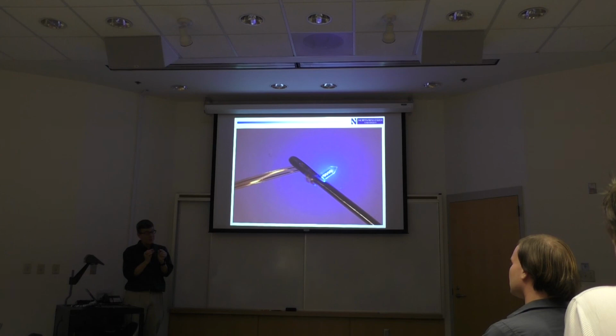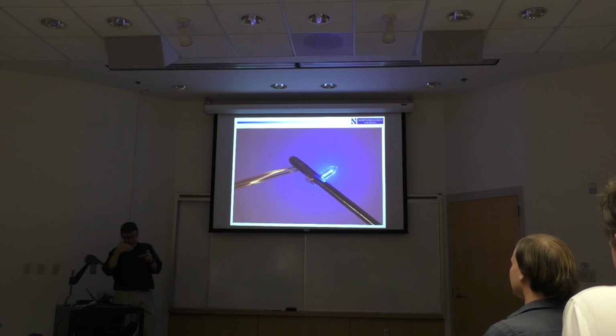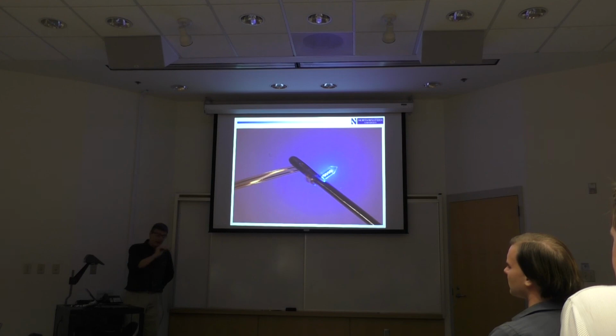And they do that because it's an effective way to keep the biofluids out. And unfortunately, we can't use that approach because 3 millimeters of titanium, and then we don't have a flexible device anymore, right? So it really has to be something that is on the order of a micron in thickness to give the kind of bendability that we need.